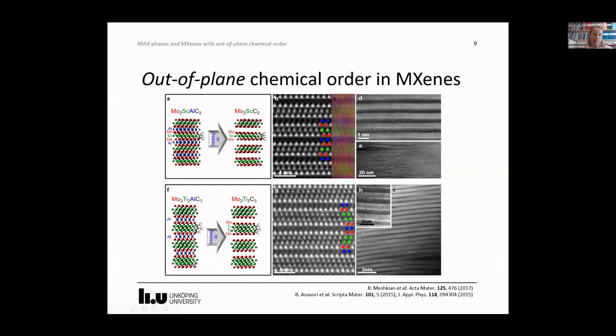The second example is a 413, moly-2 titanium-2 aluminum carbide. And here you can actually see the chemical ordering in the MAX phase due to the Z contrast, which you can actually also see when it has been converted into a MXene.